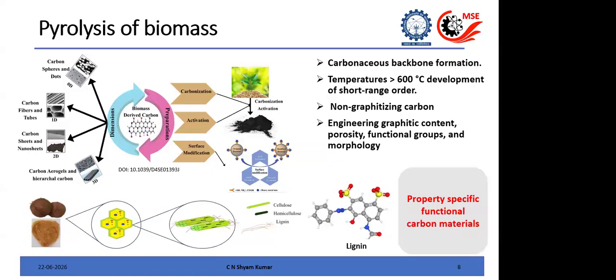There are groups working on engineering the polymer itself to have more graphitic content, self-assembled monomers and all, so that you have more aromatic rings, and finally you can tune the graphitic content. But here, what we started is to look into the biomass, because biomass inherently is lignocellulose, so it contains lignin, cellulose, and hemicellulose.